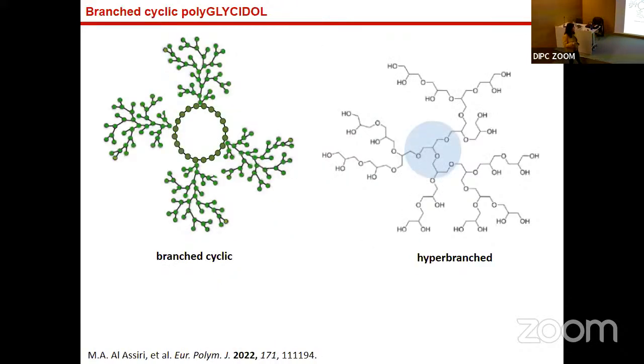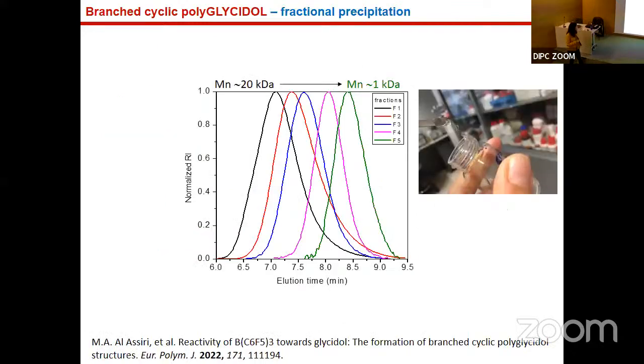However, what we get is something depicted here as a branched cyclic polymer with a lot of branches full of hydroxyl groups, which resembles the hyperbranched polyglycidol, very much studied in the literature for biomedical applications because of the possibility of modifying these hydroxyl groups. And this is what we are doing. We are trying to use this cyclic polyglycidol, which is synthesized very easily just by putting in the monomer and the catalyst, and we get the polymer. A high amount of polymer is here. It's very viscous.